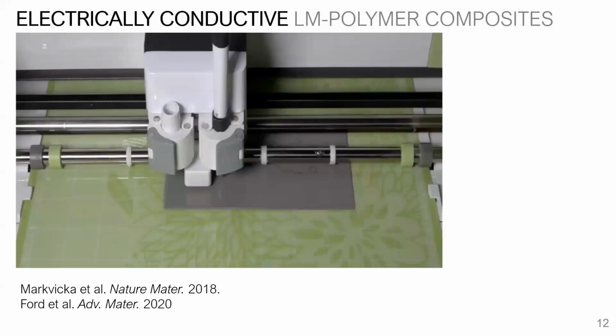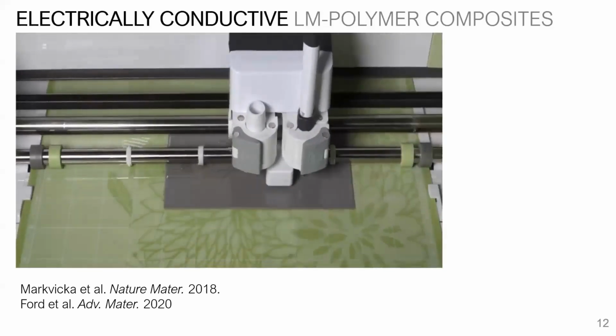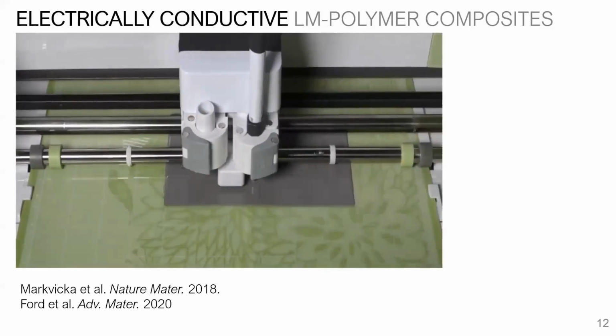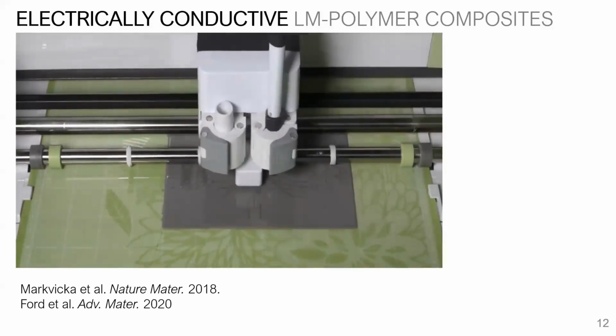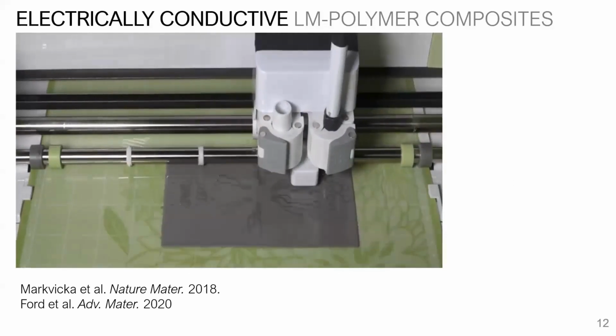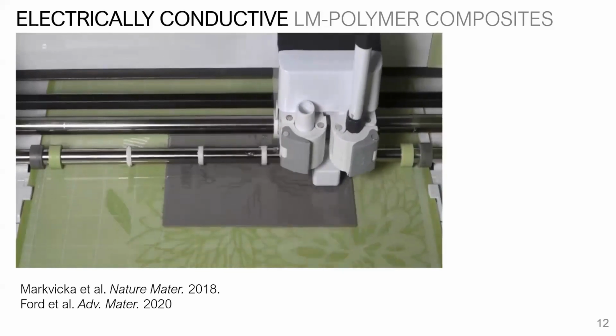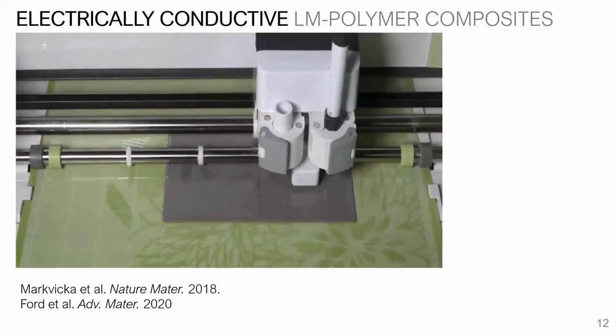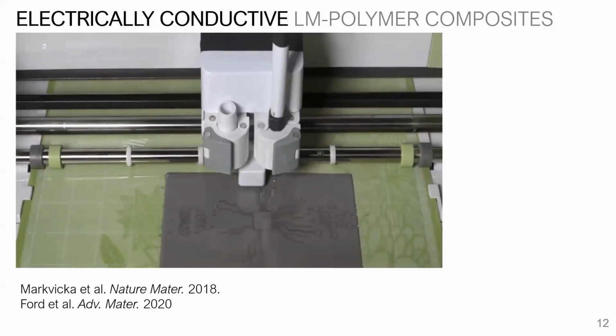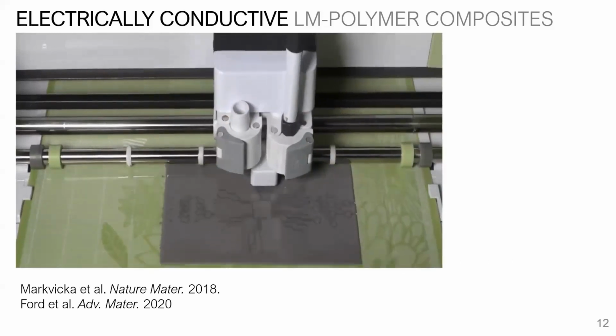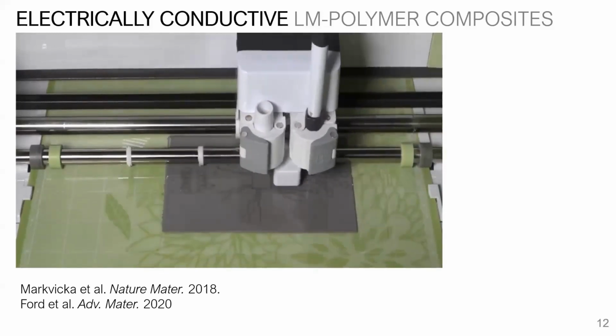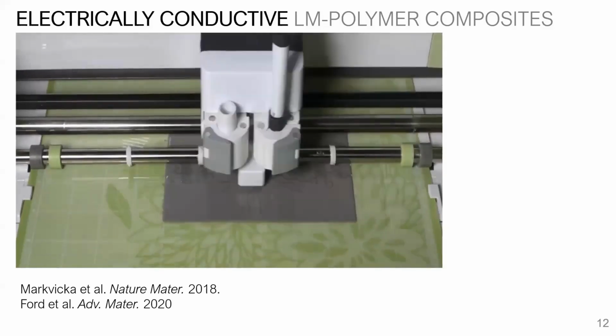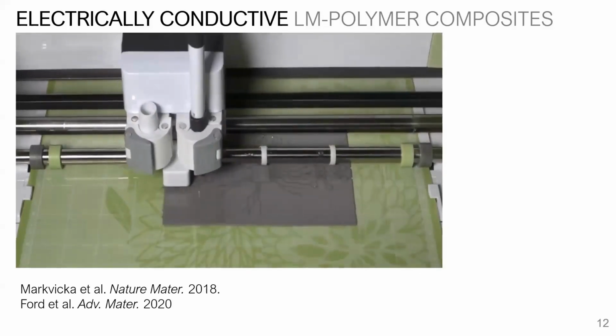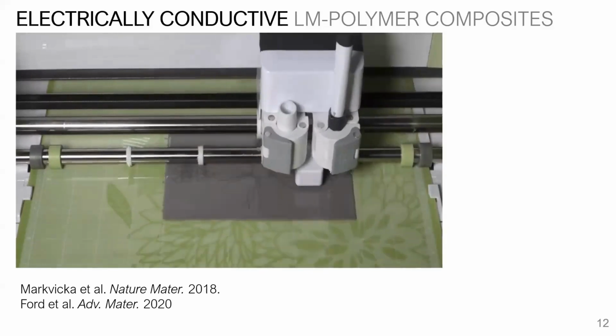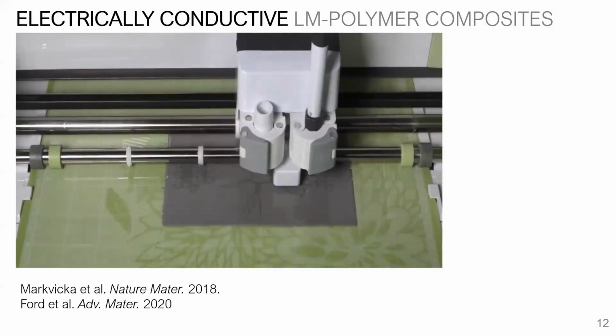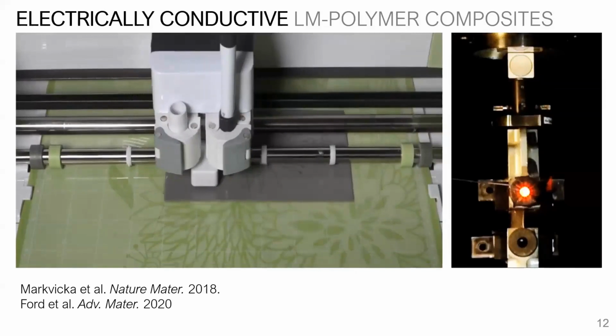Then, to get these droplets to connect, we have to do a so-called mechanical sintering process, which is a little bit messy. Some of you who've had experience with this, like Watson, with whom we've worked on creating these stretchable RF devices, know this. It looks clean here where we use this Cricut pen plotter, but in practice, sometimes you have to apply really intense pressure to get those liquid metal droplets to rupture and connect with their neighbors. So not really the best thing.